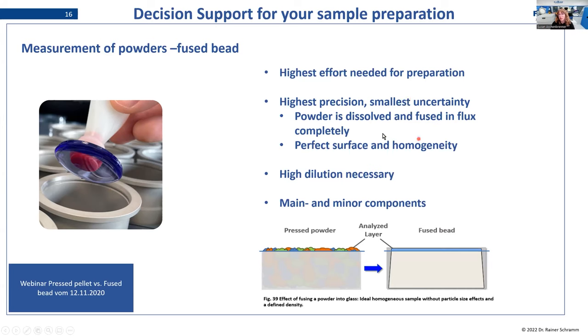And this is because of the total dissolved powder that is fused in the flux completely. So we are not having any molecular structures anymore. We are not having any particles anymore. It's really, truly, completely dissolved in this flux. And then we are creating, by pouring it into a mold, a perfect surface and a perfect homogeneity. Here below, you can see a comparison between pressed powder and fused bead. And you can see that all the effects that we have with pressed powders or just measuring in a sample cup are gone when we are measuring a fused bead.